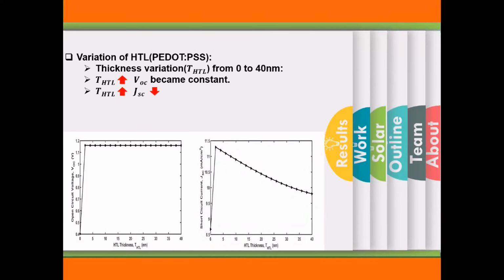Next, we kept the absorber thickness at 100 nanometer and varied the thickness of the HTL from 0 to 40 nanometer. We get this result. We can see from the open circuit voltage curve that while the thickness of the HTL is increasing, the open circuit voltage becomes constant. For the short circuit current density curve, when the thickness of the HTL is increasing, the short circuit current density is decreasing.